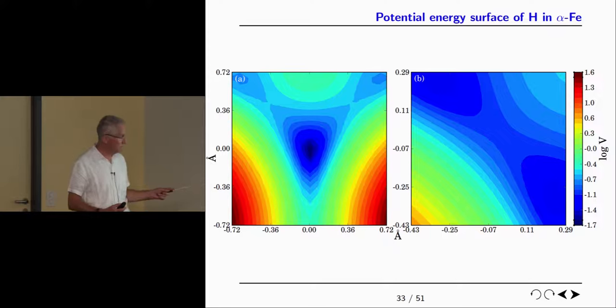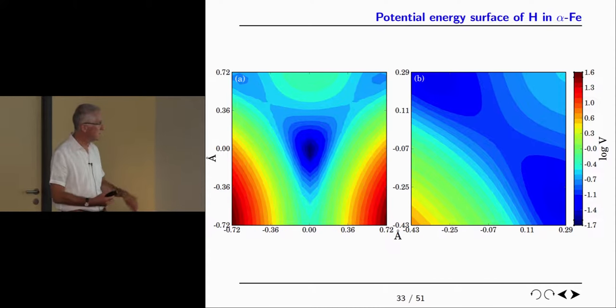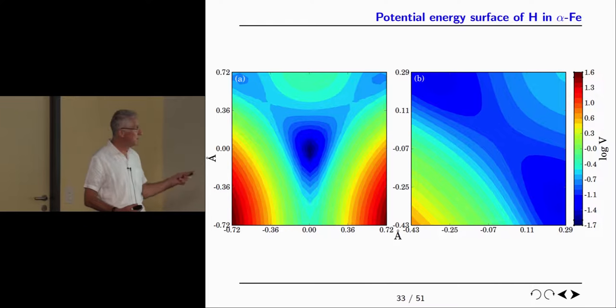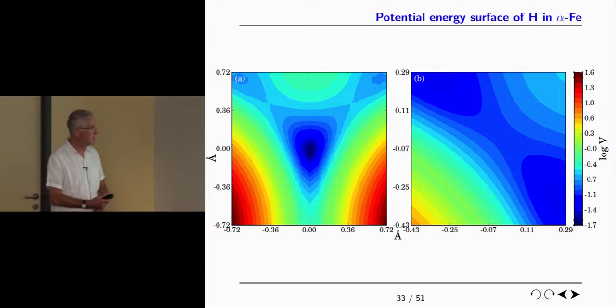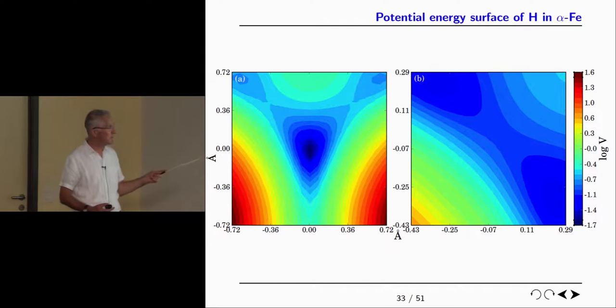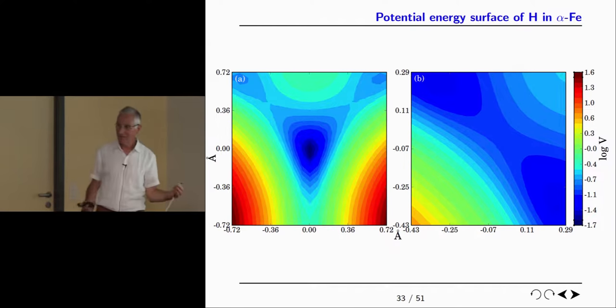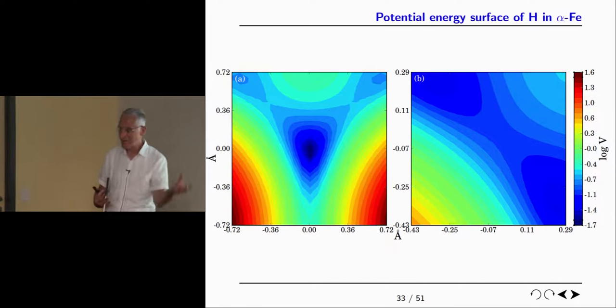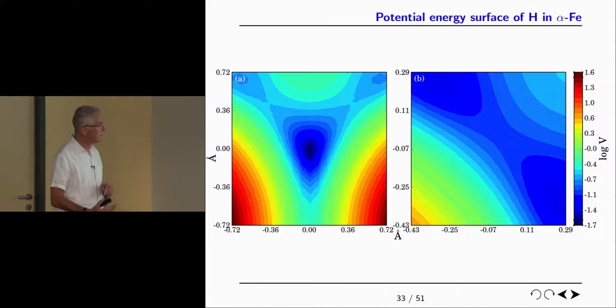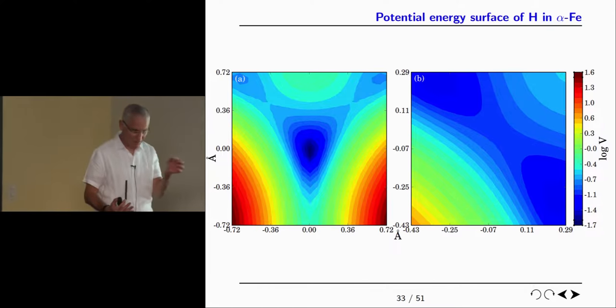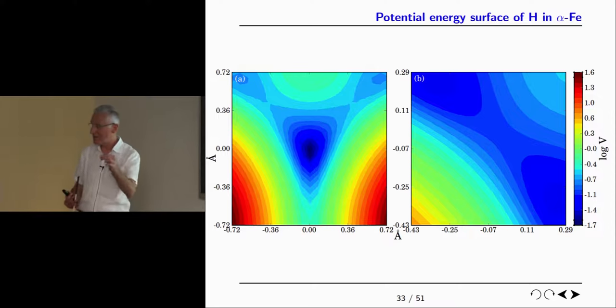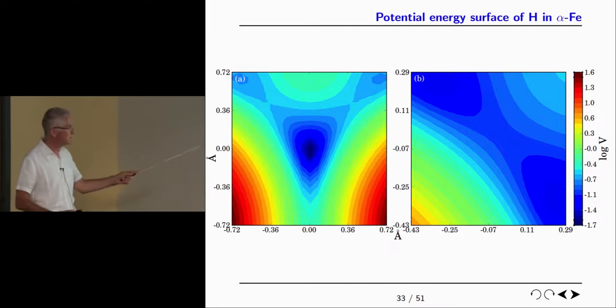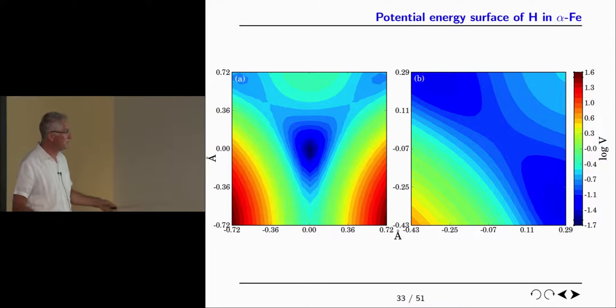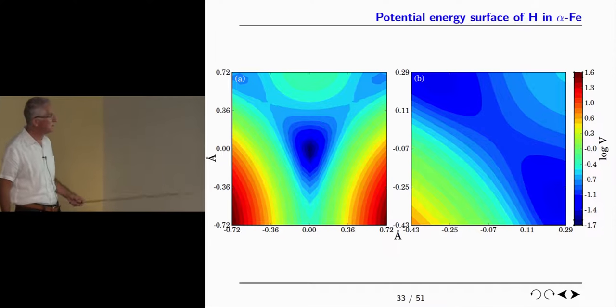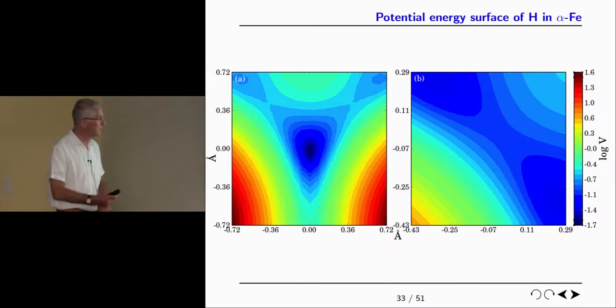So what we did was, well, Ivo, this is now Ivailo's work, I showed you him a moment ago in the photograph, he would take a reasonably large supercell, 16 atoms of iron, and he'd put a hydrogen atom into a tetrahedral site, and he'd relax the iron atoms around that. So it's sitting in a relaxed configuration. And then he would leave those iron atoms fixed, and he would simply explore the energy surface by moving the hydrogen atom around and calculating the total energy to produce, in this case, a three-dimensional energy map, but this is a contour plot of a section through it. So that we put to one side, and we keep that for further use.